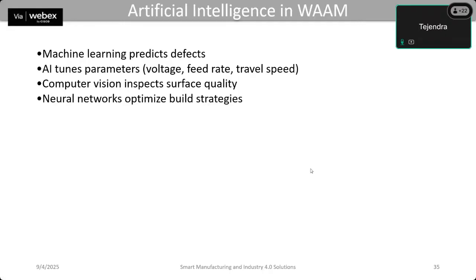Secondly, the AI can tune the process parameters in real time. For example, it can adjust the voltage, the wire feed speed, or the torch travel speed automatically to maintain stable deposition and consistent bead morphology. Also, computer vision systems use cameras to inspect the surface quality of each layer. They can detect irregularities like roughness or incomplete fusion, immediately avoiding build failure. And also, neural networks can be trained to develop optimized build strategies. Instead of trial and error experimentation, AI can suggest the best combination of parameters for a specific material, geometry or application.